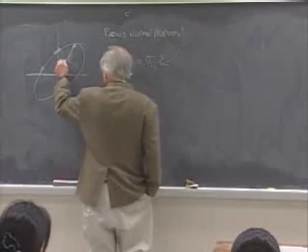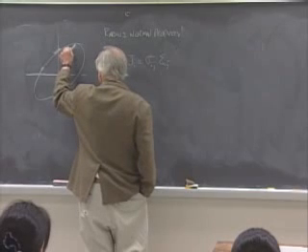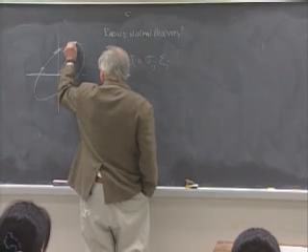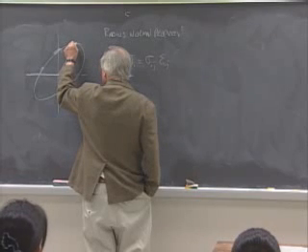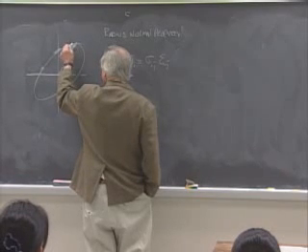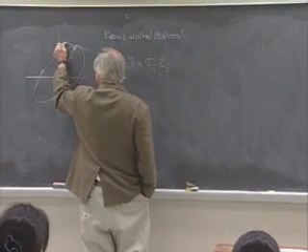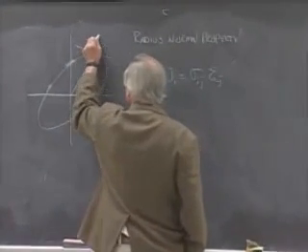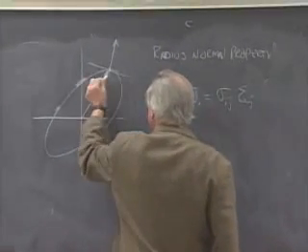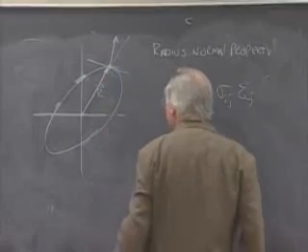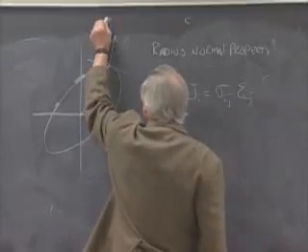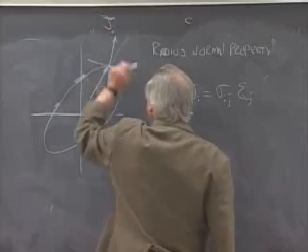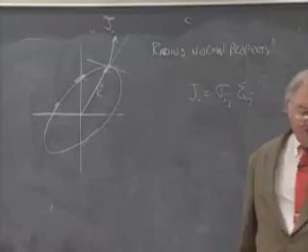The radius normal property is that if you want to know where J is for this particular direction, look at the point where the radius vector intersects the surface of the quadric, and at that point construct a perpendicular to the surface, which in general will not be parallel to R, and this will be the direction of J. It won't give you the magnitude, but it'll give you the direction of it.